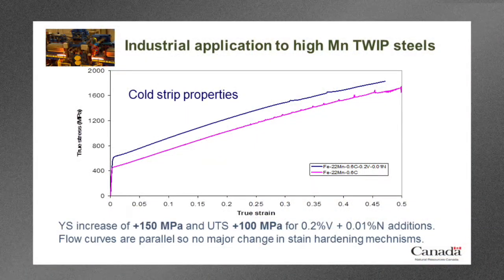I've shown you that the hot strip properties didn't change as a function of the amount of vanadium added. Well, the cold strip properties certainly do. This is an example, again, industrial steel, where we had a reference steel with 22 manganese, 0.6 carbon, which would be the pink colored curve, and the same steel but microalloyed with 0.2 vanadium and 100 ppm of nitrogen. And you can see that we got a strong increase in yield strength, 150 megapascals, and a 100 megapascal increase in the ultimate tensile strength. The flow curves are more or less parallel, so there's no major change in the strain hardening mechanism.